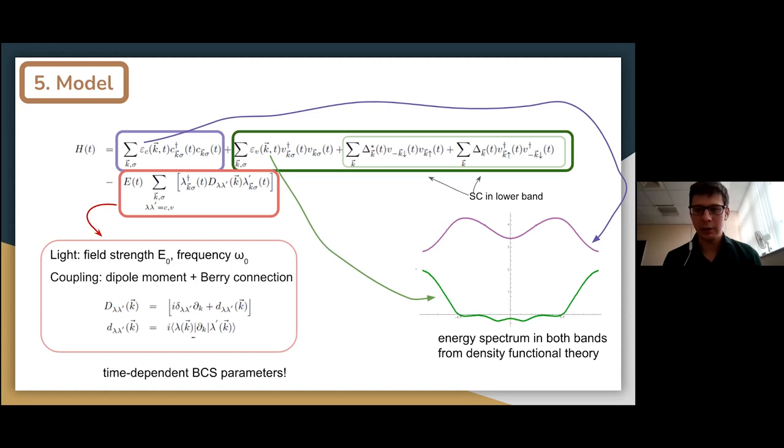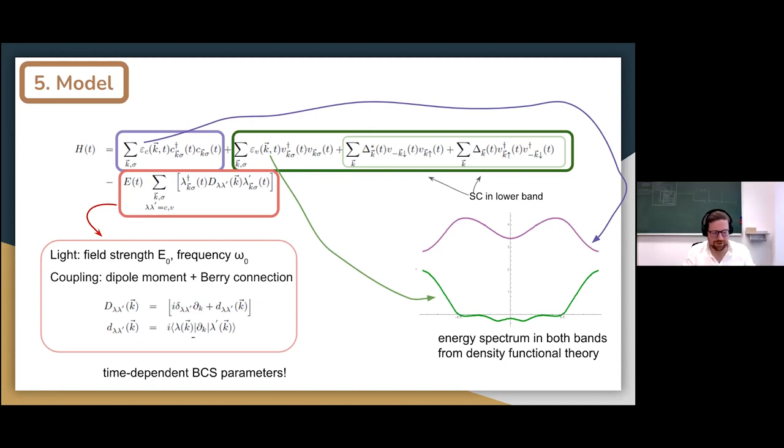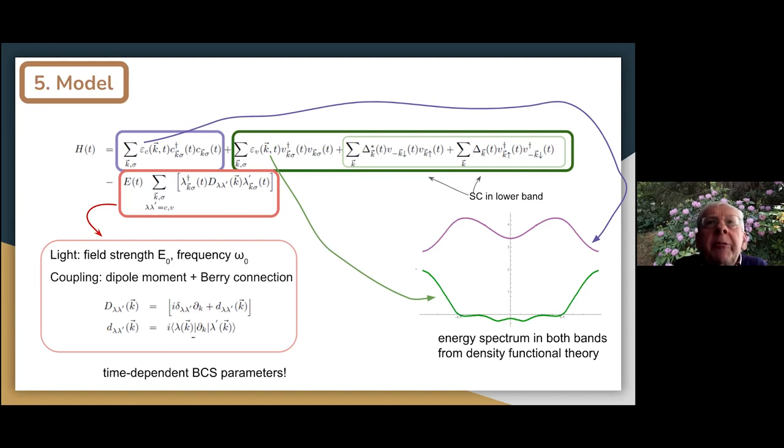So we'll check. Are there any other questions? I'm looking at raised hands. Experimental question, I probably missed it. Do you have magnetization data for that sample as a function of temperature? Let me look at the supplemental materials. I do not, sorry. Because that's a very basic thing: how much of the volume of the sample is really in the superconducting state when you lower the temperature? The whole sample is usually, at very low temperatures, liquid helium and below, fully superconducting.